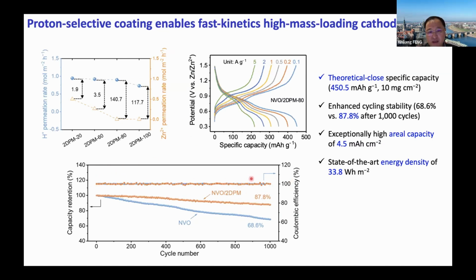So with the proton intercalation chemistry, we also improve the capacity retention to more than 80% up to 1,000 cycles, and we can still achieve very high theoretical capacity and energy density for this device.